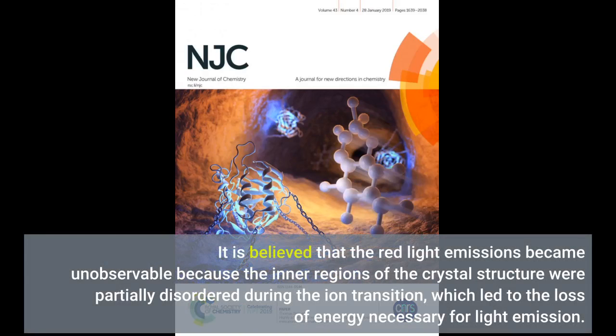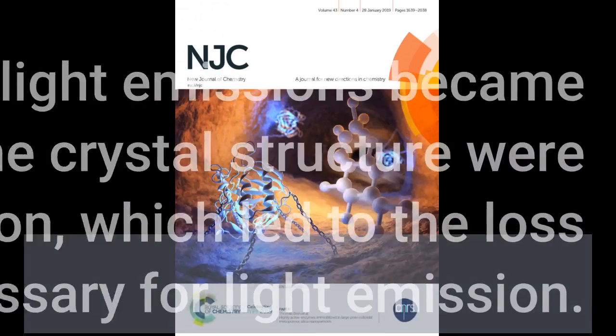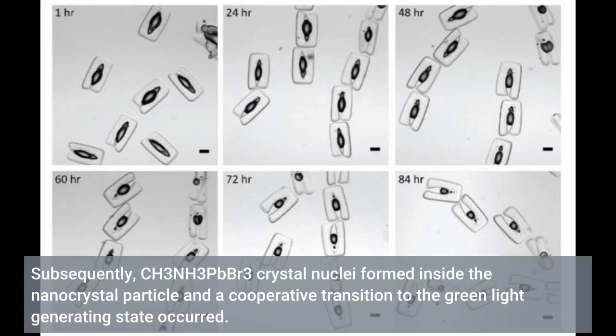It is believed that the red light emissions became unobservable because the inner regions of the crystal structure were partially disordered during the ion transition, which led to the loss of energy necessary for light emission. Subsequently, CH3NH3PbBr3 crystal nuclei formed inside the nanocrystal particle and a cooperative transition to the green light generating state occurred.